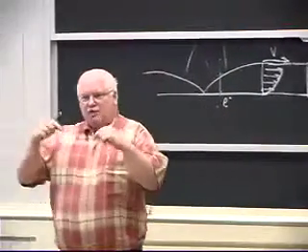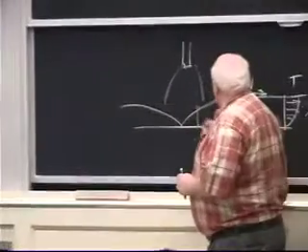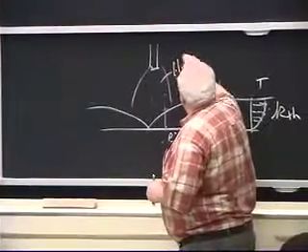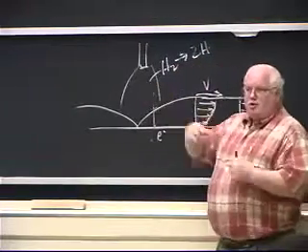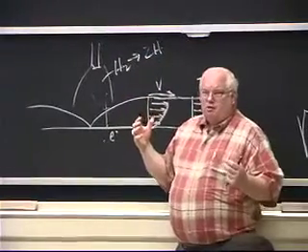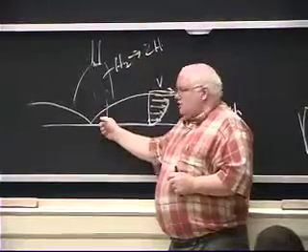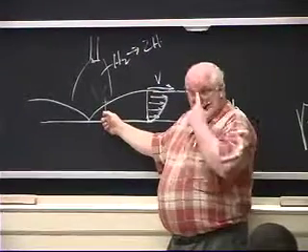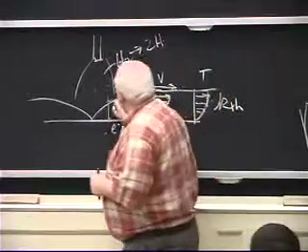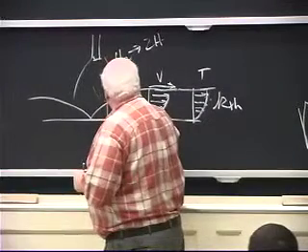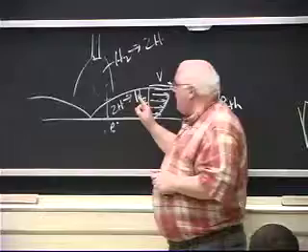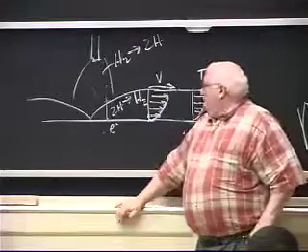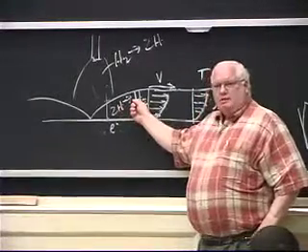Hydrogen carries the heat of recombination. Up in the middle of this plasma, I'm dissociating hydrogen into monatomic hydrogen. It takes energy to do that, to break apart the hydrogen diatomic molecule. When it gets down in this relatively cool boundary layer at 3,000 degrees, the monatomic hydrogen recombines into diatomic hydrogen. And when it does that, it gives up heat.